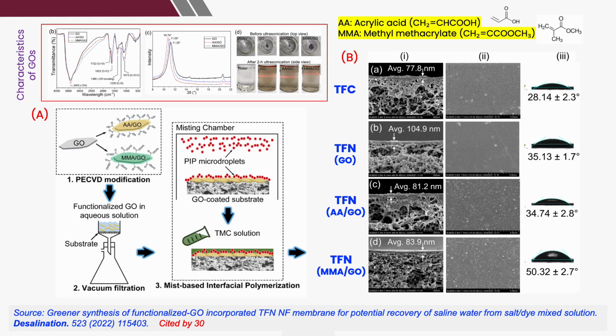Using the mixed IP technique, we further develop the thin film nanocomposite membrane incorporating graphene oxide with and without modifications. So this is an SEM physical image of the different membranes. The TFC membrane is a control membrane made of mixed IP, and when you have graphene oxide within the thin film polyamide layer, the thickness of the layer increases.